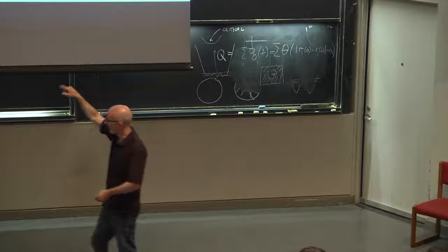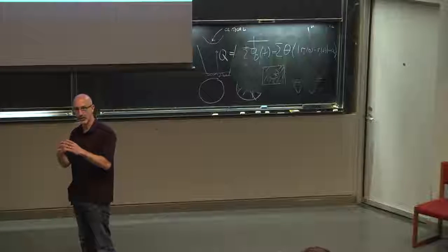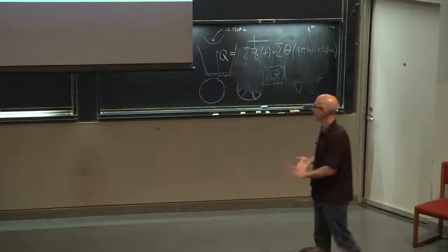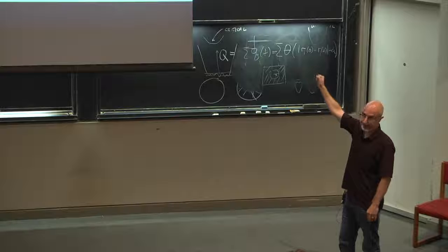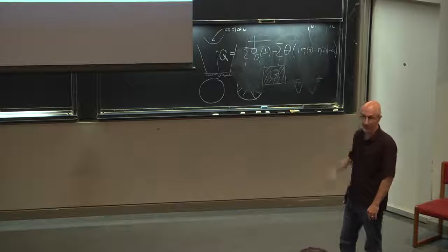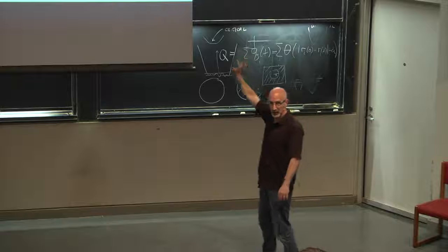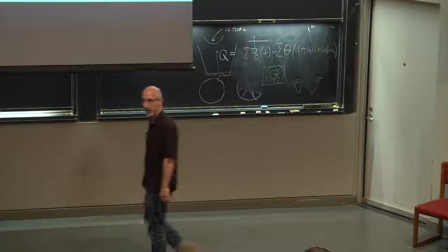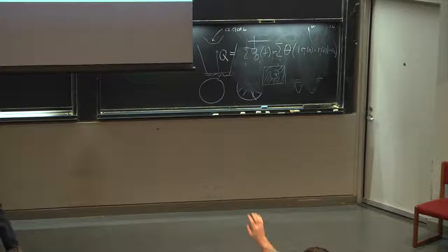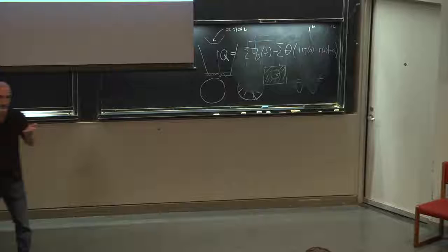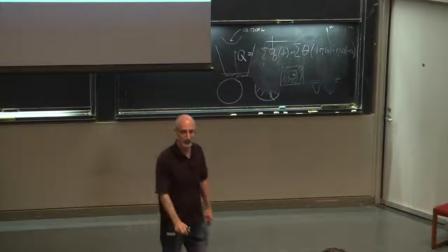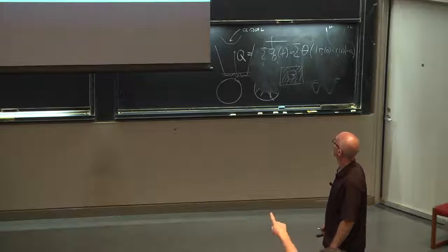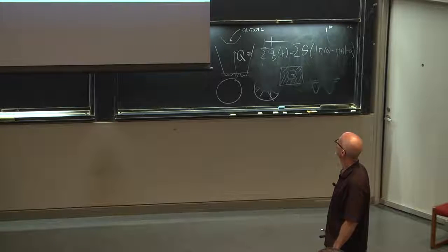It does get very, very hard to sample the configurations for small cavities, and you have to do the sampling well. But if you do this carefully, and there are checks to see that you've done it carefully, then you can extract this length scale, and it is growing, at least in the regime associated with the computer simulations we can do. It's growing in a way that's different than the dynamical length scale, and this is again a prediction of the mean field theory. When I look at that one, it seems that it goes up to, I don't know, 4 maybe. And when I look at the purple one, it's less.